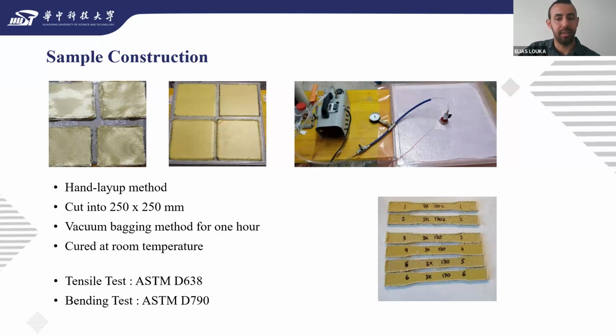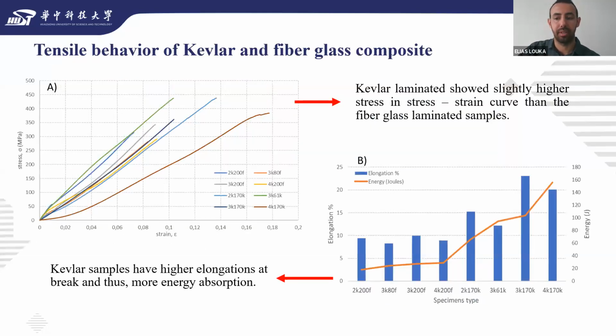Now we are moving to the tensile behavior. To determine the mechanical properties of the composite, tensile tests were conducted on the fiberglass epoxy matrix composite and Kevlar epoxy matrix composite. Figure A shows a typical stress-strain curve obtained by the fiberglass and Kevlar samples. Samples were laminated with different numbers of layers according to the requested fiber total mass. Kevlar laminate showed slightly higher strength in the stress-strain curve than the fiberglass laminate sample.